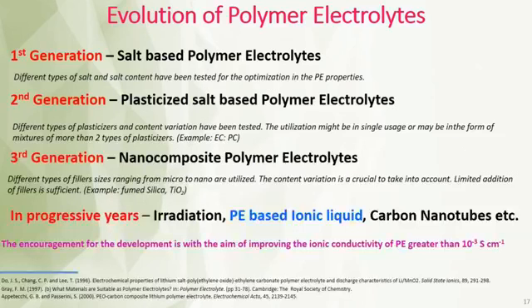Okay, I want to share with you all the evolution of polymer electrolytes. The first generation polymer electrolytes are generally salt-based polymer electrolytes. The researchers found that even though the salt can change the polymer from an insulator to a conductor, the conductivity values are not sufficient to be used for electrochemical devices. So that's where they came to the second generation, using plasticizers to enhance the ionic conductivity of the polymer electrolytes. But again, the problem is that plasticizers can decrease the mechanical properties.